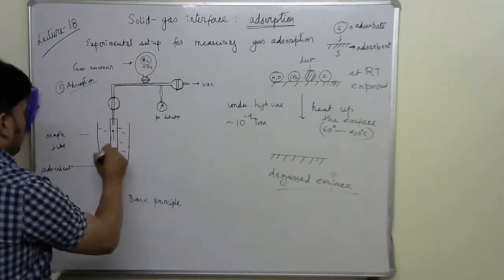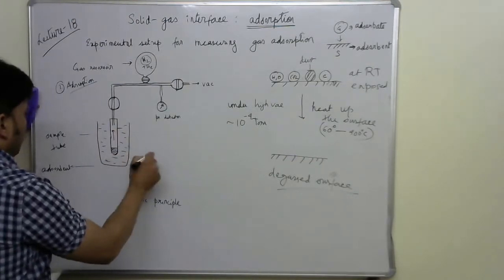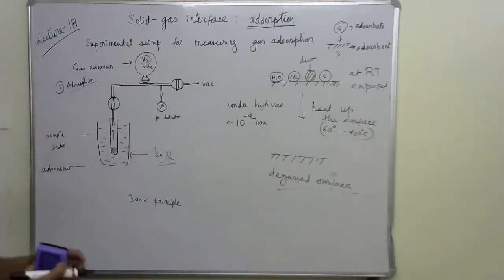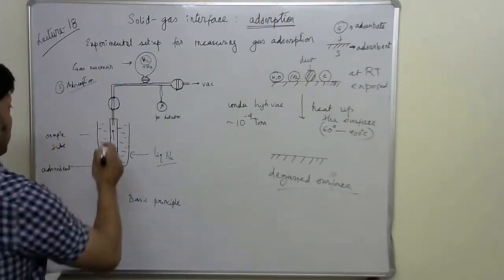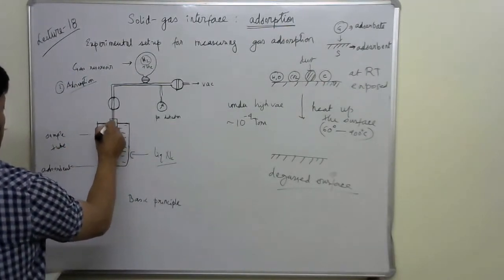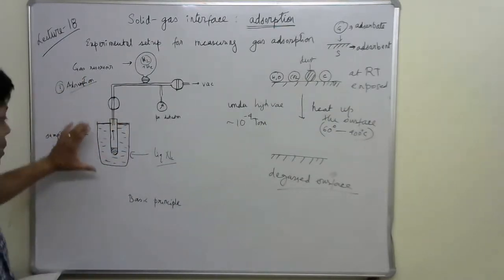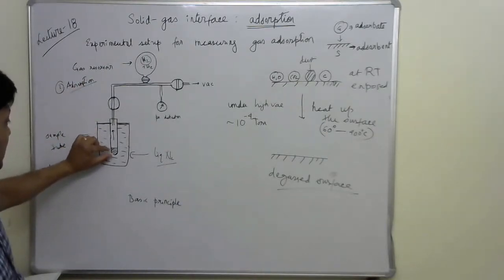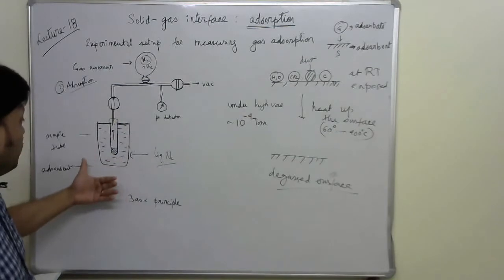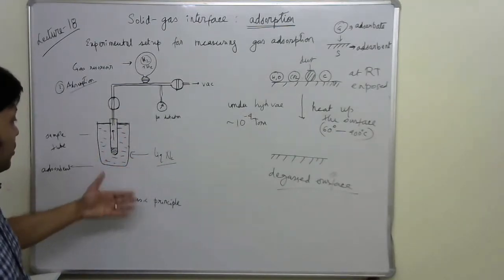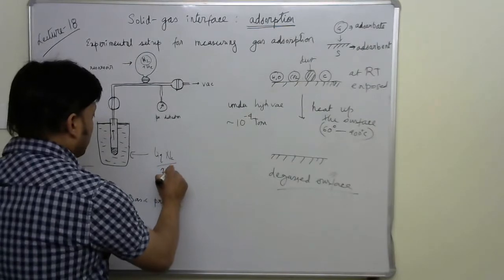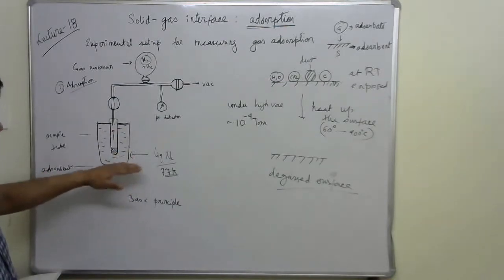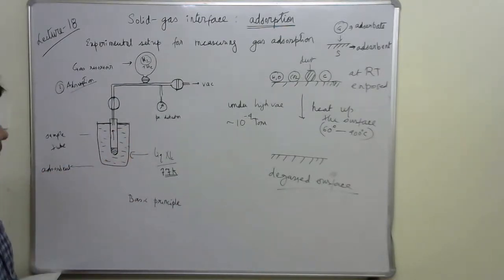Okay, so there will be a thermoflask, and those thermoflasks contain liquid nitrogen. Gradually the sample tube is lowered into the liquid nitrogen container and the top portion is filled. Now this entire gas tube is under liquid nitrogen, and some time is allowed so that the temperature inside the sample gets equilibrated with the liquid nitrogen temperature. The liquid nitrogen temperature is basically 77 Kelvin. So all the adsorption experiments are usually carried out at 77 Kelvin.